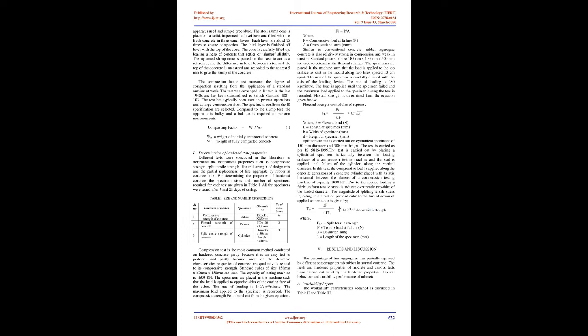According to his analysis, the addition of crumb tire rubber volume fractions up to 5% in a cement matrix does not imply a significant variation in the concrete mechanical features, either maximum stresses or elastic modulus. The mechanical static test results for compressive, indirect tension (Brazilian method), and 4-point bending strength on standard specimens with fiber reinforcement concrete at 7 and 28 days showed an admissible dispersion as compared to the control mix.